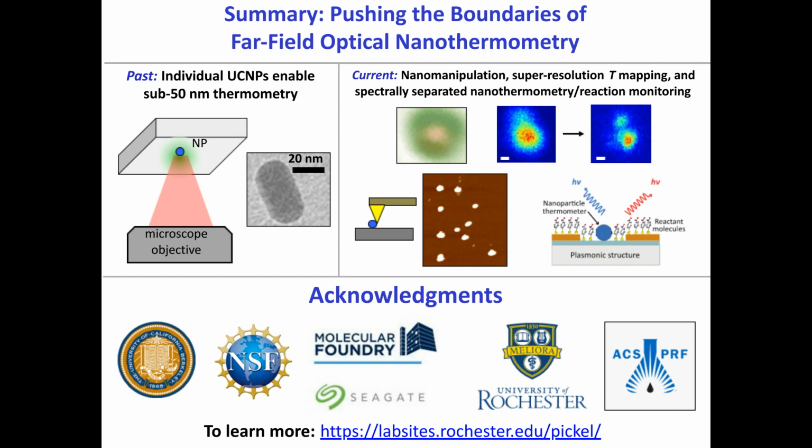And they actually see that the ratio values that you get as a function of temperature are extremely similar to what you get in a more conventional non-plasmonic environment. So that's a helpful precedent there. You get some enhancement in the overall brightness, which is actually a big advantage perhaps, but you don't see distortions of the ratio.